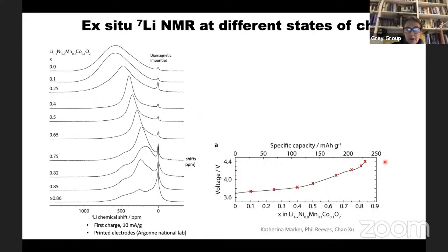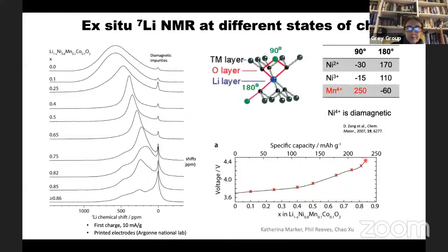So what we do, not surprisingly, to understand this is NMR spectroscopy. So here's the NMR now, and this is not in situ. This is where we make lots of different batteries and we take them apart and run them individually to get better high resolution spectra. So here's the broad signal for the original material, and this is the one at the top of state of charge. And so you can see this battery is operating at somewhere between 3.7 and 4.4 volts.